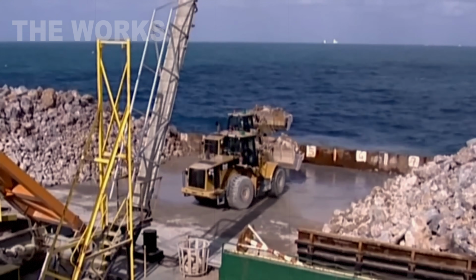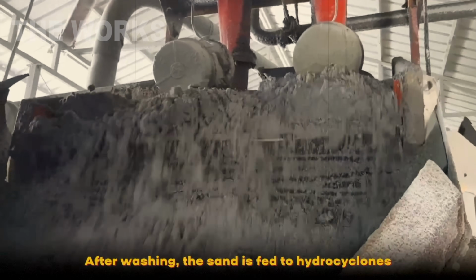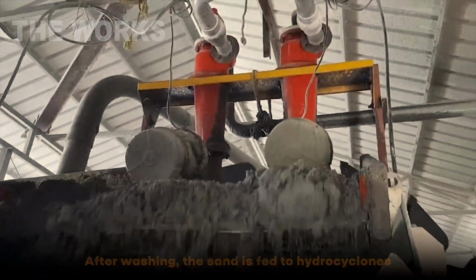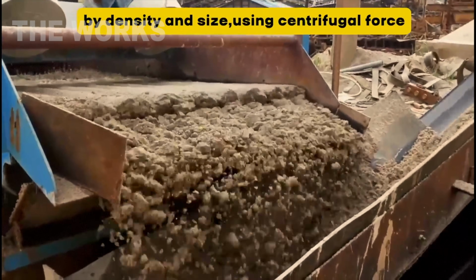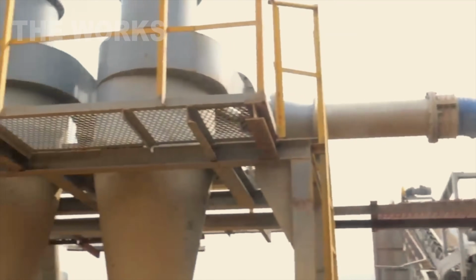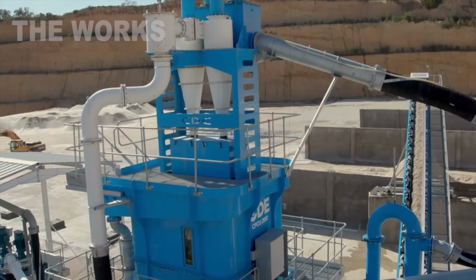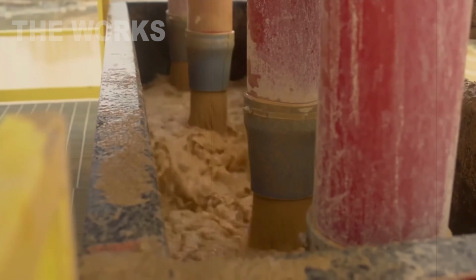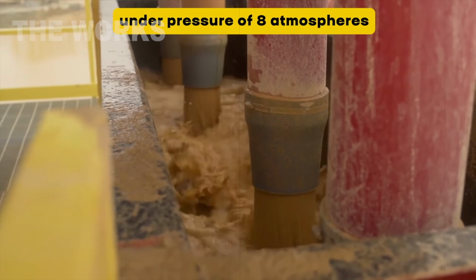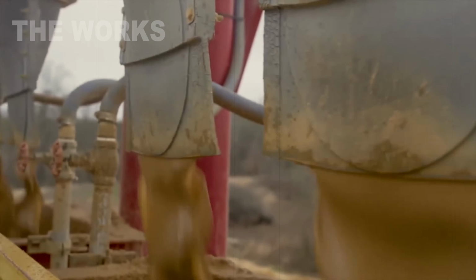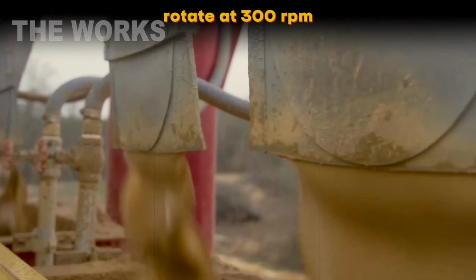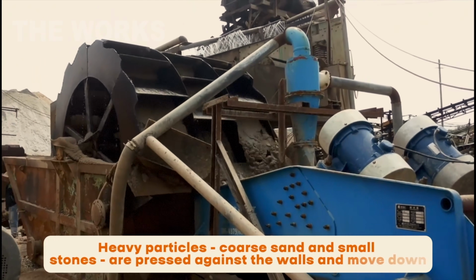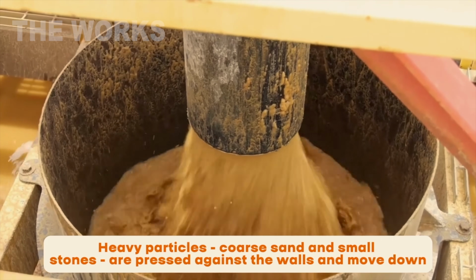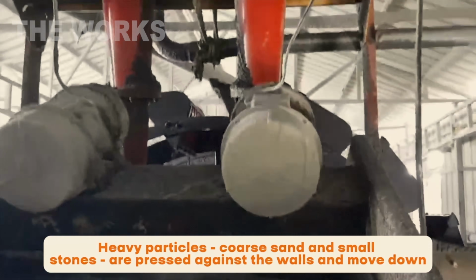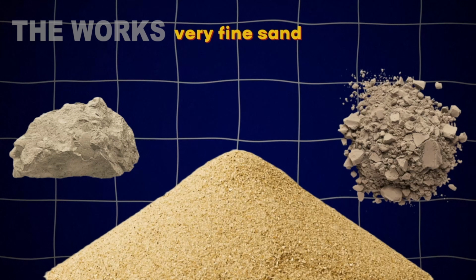After washing, the sand moves to hydrocyclones, devices that separate material by density and size using centrifugal force. Picture giant metal cones 20 feet tall. The slurry gets pumped in at a pressure of 8 atmospheres. Inside the cone, it starts spinning at 300 revolutions per minute. Heavy particles, coarse sand, and small pebbles get pressed against the walls and sink down. Light particles, silt, clay, very fine sand, get carried upward by the rising water current and get dumped as waste.